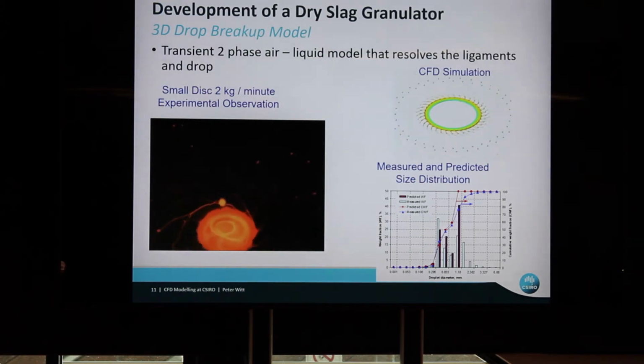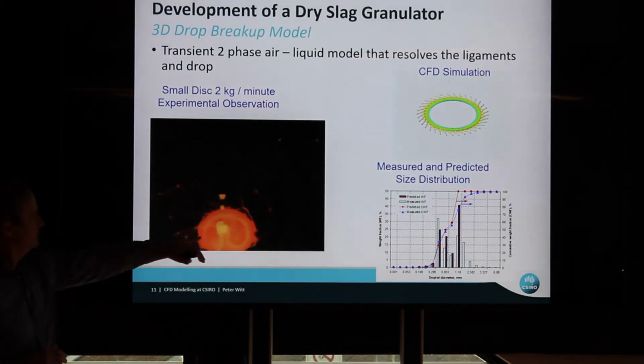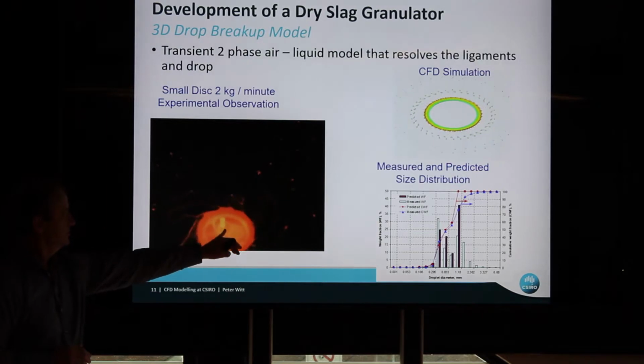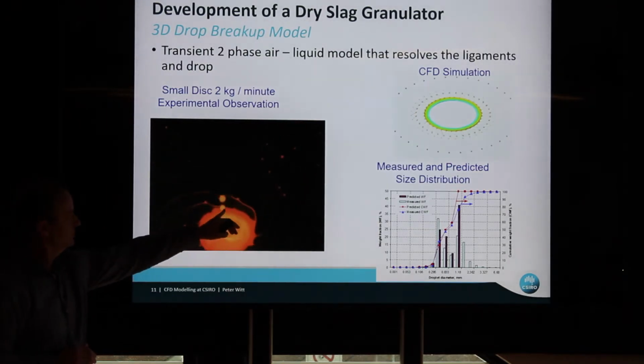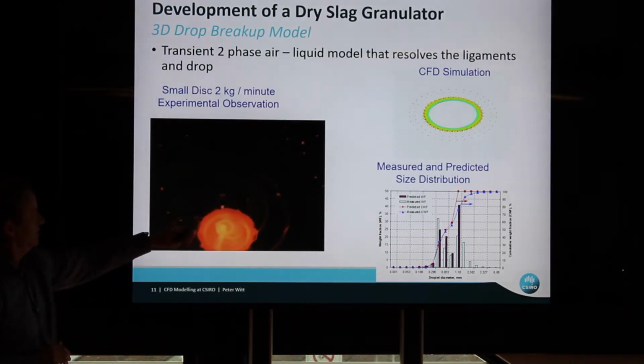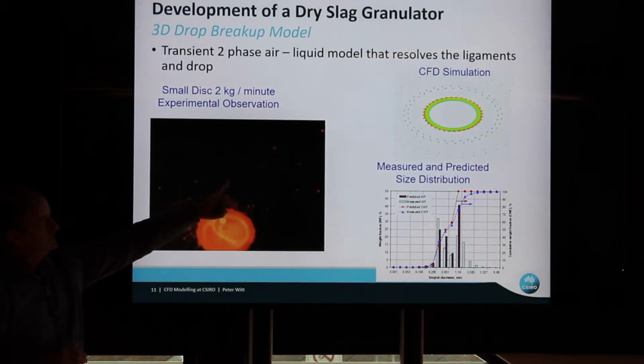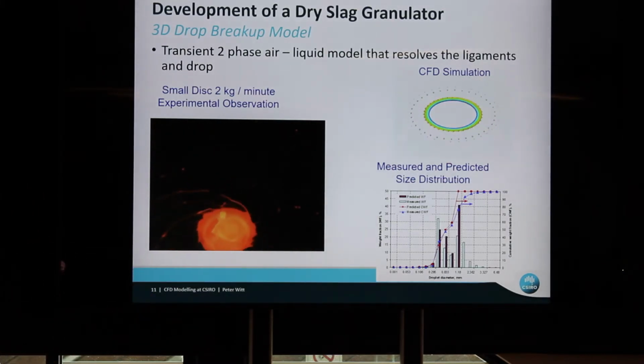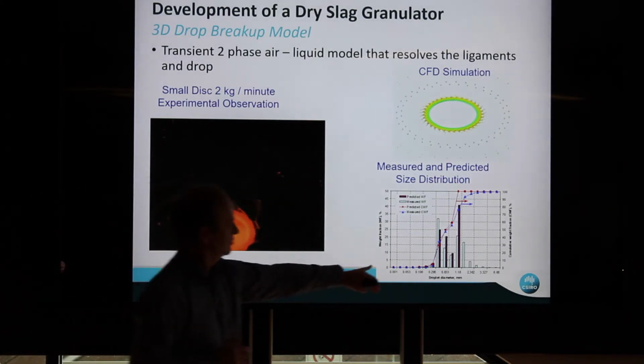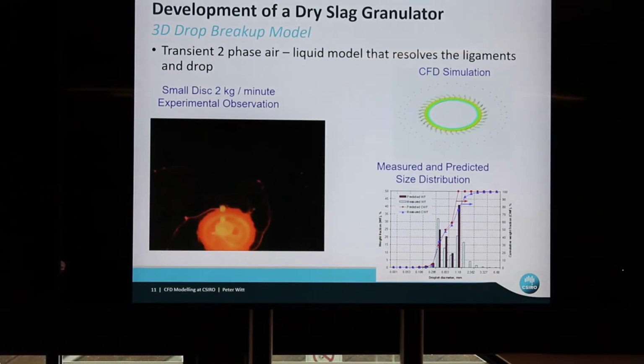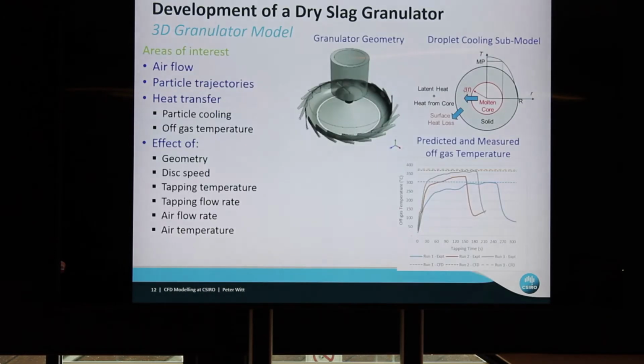The next area we tried to look at was you had the disc spinning, you have these drops of slag filming onto it, you then get these ligaments that then break up into droplets. So we did a resolved VOF type simulation looking at that, and we were able to do surprisingly well if you compared the CFD drop size prediction with the measurements of the granules produced out of the system. So we were quite happy with that.